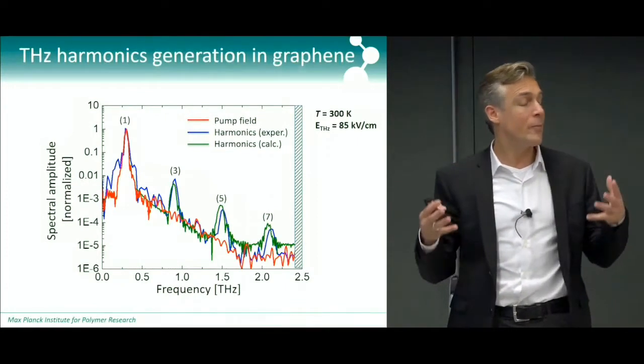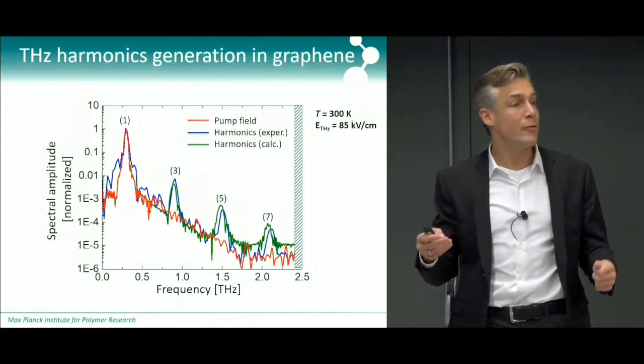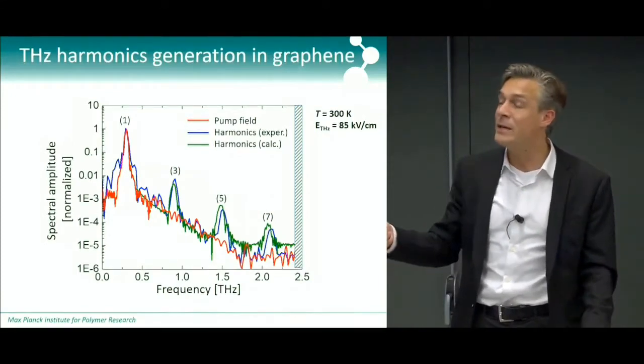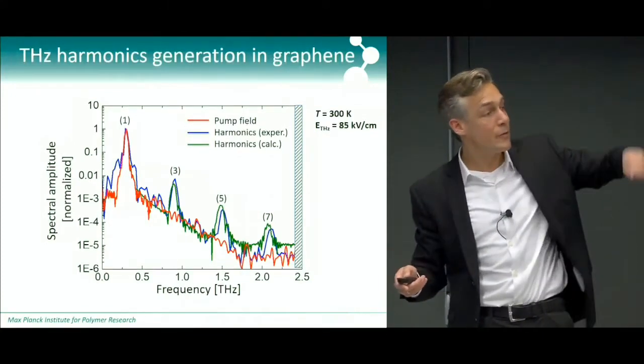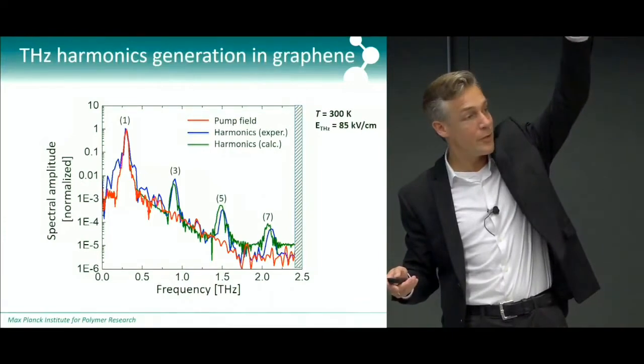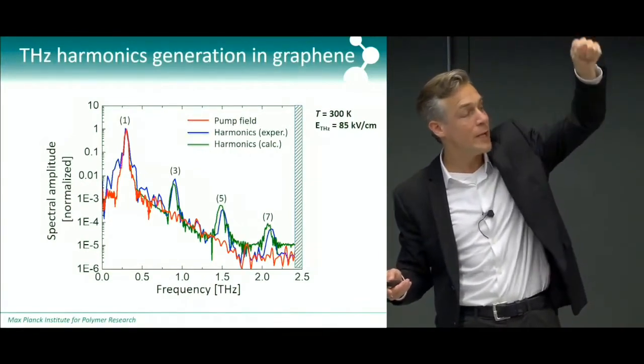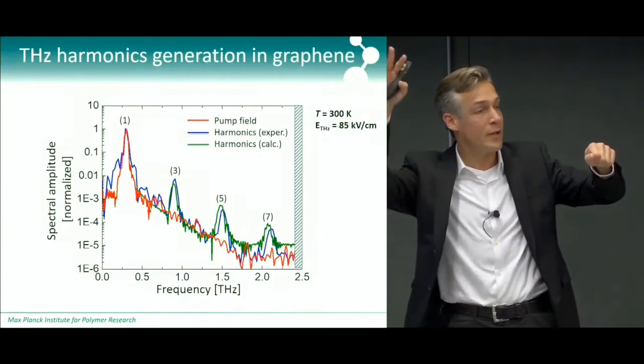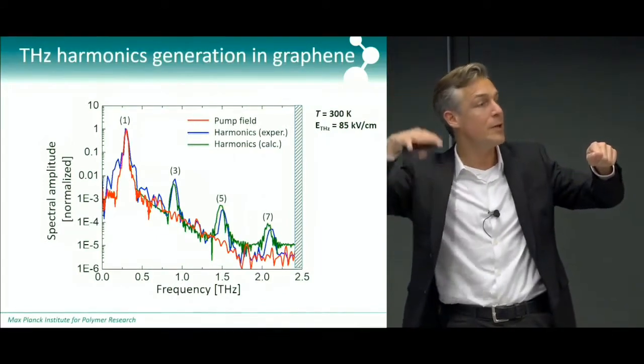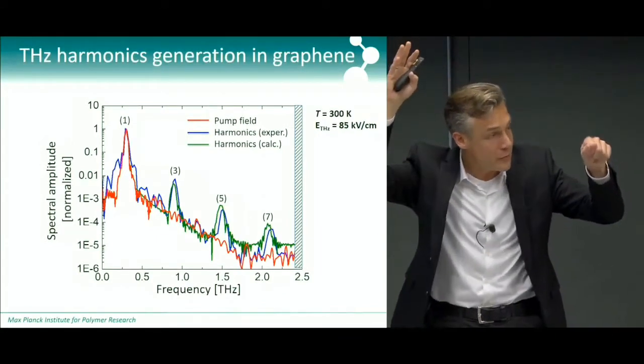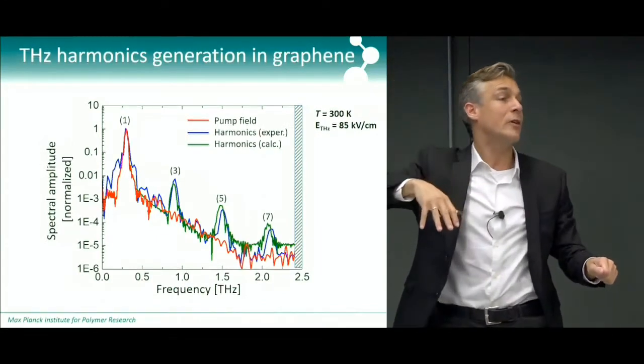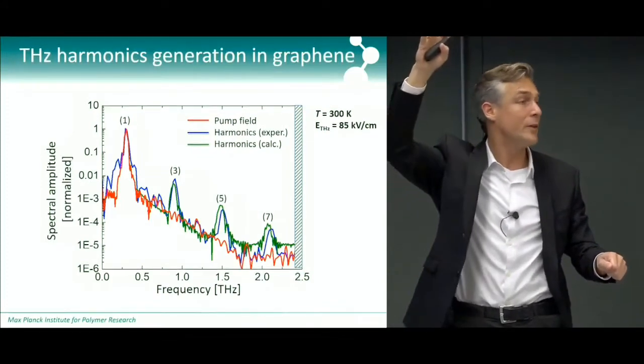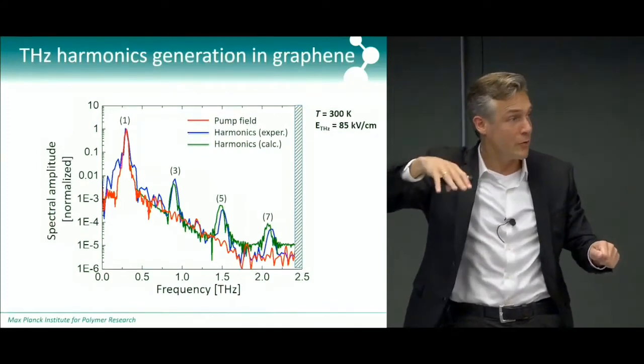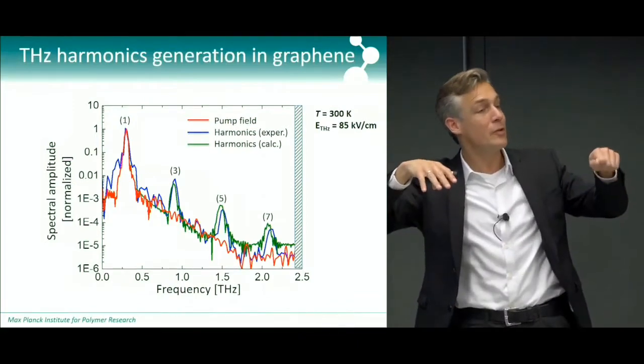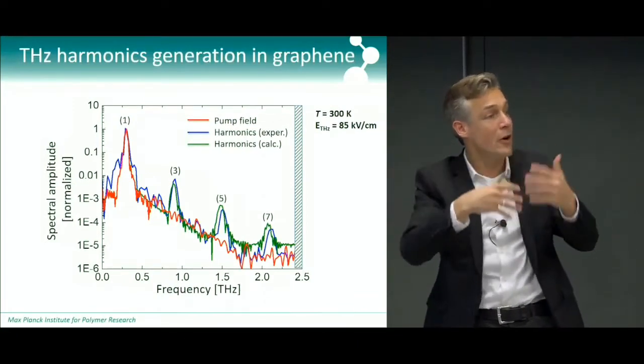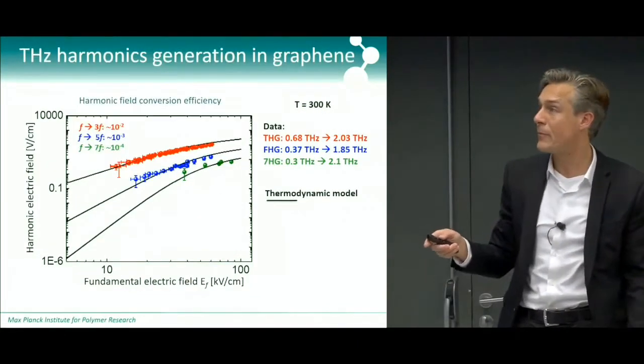generated, again, by this simple model of electrons being heated by the field in this terahertz pulse, and then as the field switches off, the electrons cool, the conductivity goes up again, then the field changes sign, the carriers are accelerated and heated, and the conductivity goes down again, and then as the field goes to zero again, and it's on and on through this cycle.